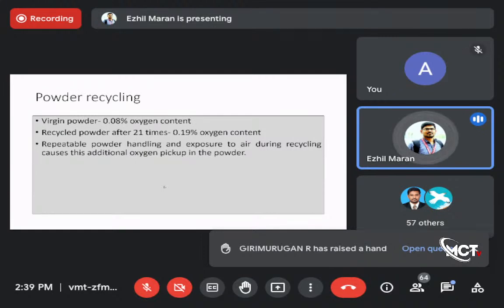So here, one statistic: recycled powder after 21 times. Initially, virgin powder contains 0.08% oxygen content. Recycled powder after 21 times, the oxygen content has increased to 0.19%. That is the issue. So you can't use the powder again and again.